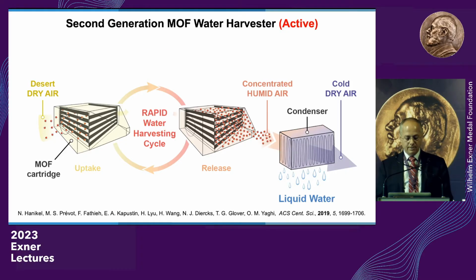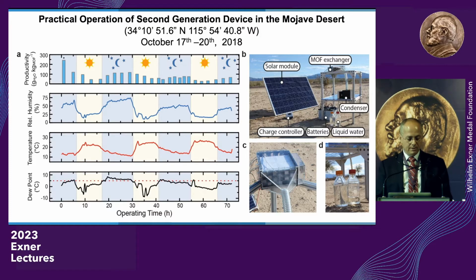And in this experiment, they went to the Mojave Desert. And here you see the humidity that they measured during the night and during the day. Okay, it's amazingly different. So during the day, it goes down to almost 10 or 7% relative humidity, but the MOF still delivers water. Okay, so this works.